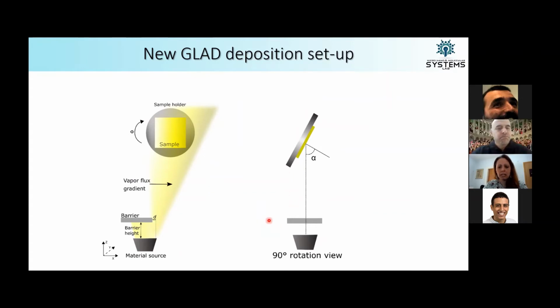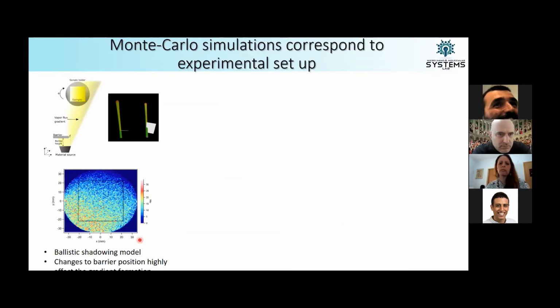So you see that basically from the side, your crucible containing the material or the material source is completely covered, and from the front view, it's partially covered, where you have a certain distance of how much is exposed of your material source and also the barrier height have a big effect. So we did some different Monte-Carlo simulations with ballistic shadowing models in order to be able to optimize this.